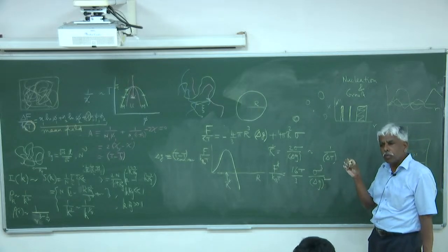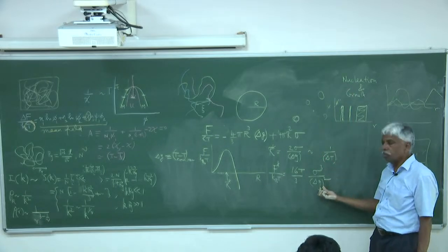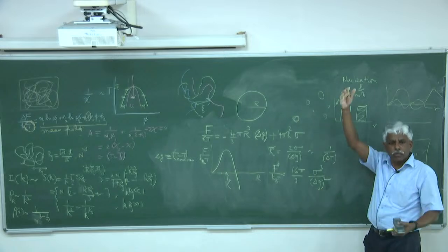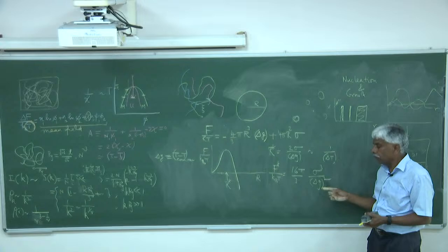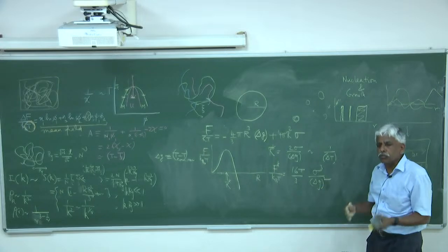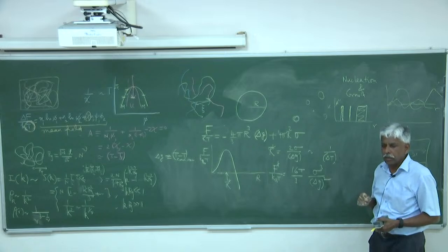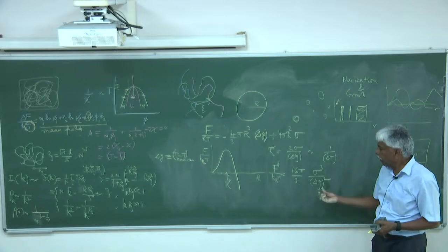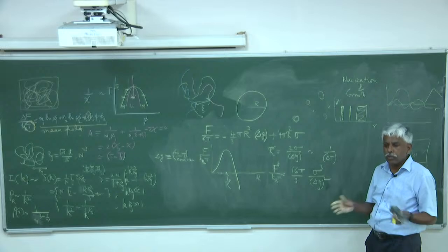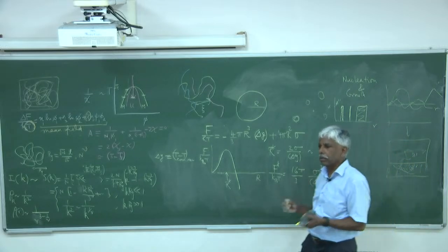So, if the quantity is small, not only do you have to make a bigger droplet, but the barrier is also very large. When delta T is small, the nucleation barrier goes to the sky. So, in order to make these droplets, you need to have delta T reasonably not small. In measurements, or if you want to do simulations, you should not just do it arbitrarily. You should design your simulation in such a way that delta T is large enough. Otherwise you will be waiting on your computer for a long time. You can go home and come back.